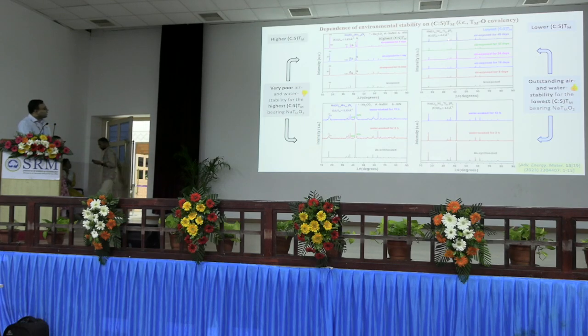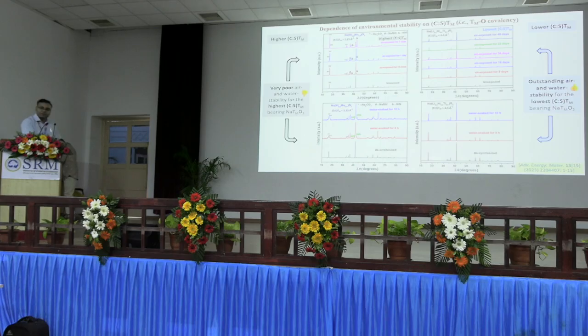Now, on the other hand, the one with the lowest charge to size ratio, which we expect to be very much air stable, is indeed so. Even upon air exposure for more than a month's time, there is no change in the XRD.